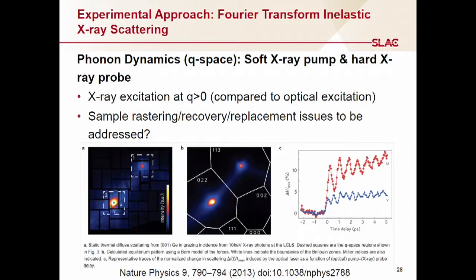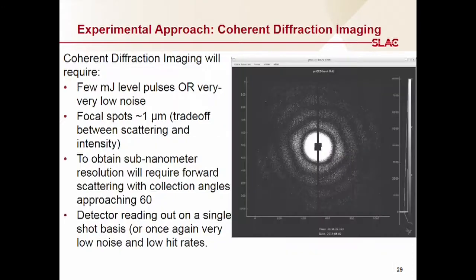Other ideas, as I said, you can think of matter under extreme conditions. We can tailor the absorption and the power to probe very extreme cases of matter. Or you can actually pluck the system very specifically. And if you're looking at just off Bragg peaks, we've done this with laser pump X-ray probe, you can actually see phonons. And you get really high resolution cases of looking at how energy transfers through a crystal. And these are also some interesting science cases we're thinking about looking at.